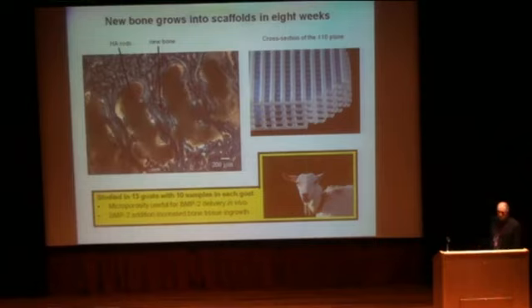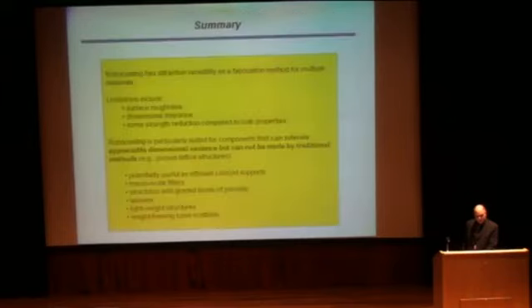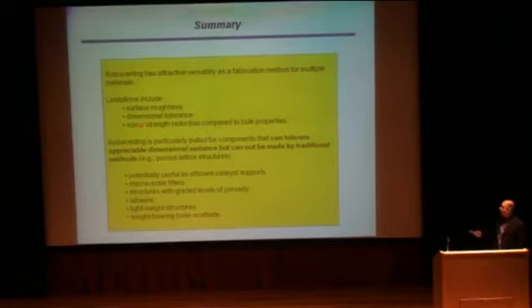And we did testing on goats, and it worked very well with new bone being grown within 8 to 12 weeks. So a quick summary on this is that we've got limitations in the process. It's not the be-all, end-all, but it does have real commercial utility for catalyst supports and filter structures in labware.